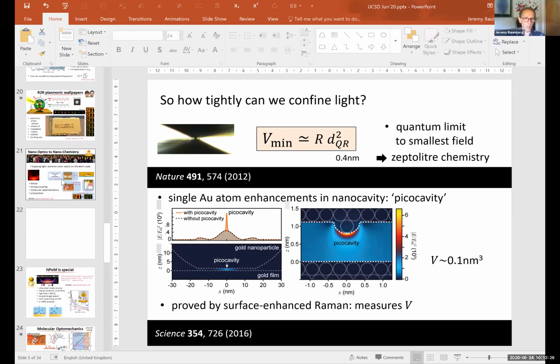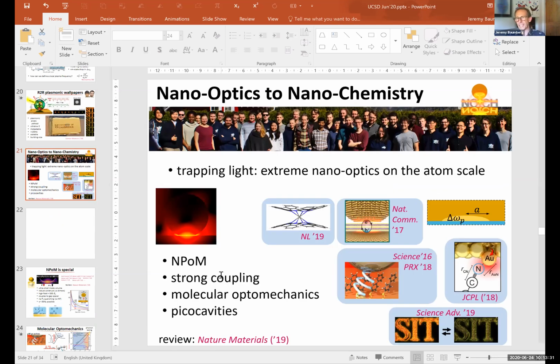Yeah, it's a very good question. The main difficulty is that I showed you that the mode is vertically polarized here. If the mode is vertically polarized, it can't carry any chirality. So you have to make a more complicated system to do that. So, for example, can we use a cube or more such nanoparticles? If you don't want to use the vertical mode, then you can do it. But the problem is if you're using the cube, you have to use a bigger gap because then you want the in-plane mode and that gets squeezed to very low energies.